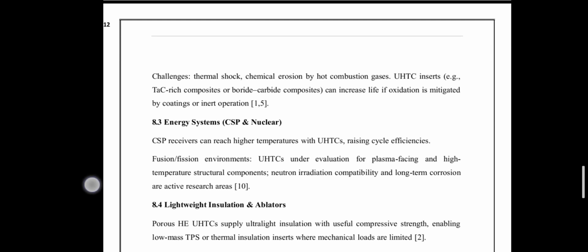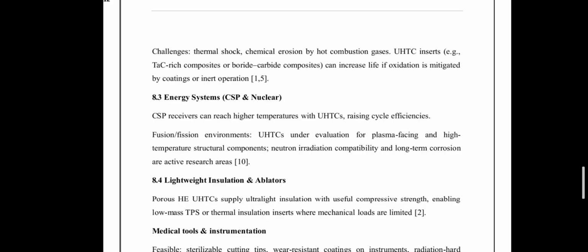So next we will study the energy systems, concentrated solar and nuclear, where the ultra high temperature ceramics are used. Ultra high temperature ceramics allow receivers to reach higher temperatures, improving the thermodynamic cycle efficiency. In fusion reactors, ultra high temperature ceramics are under evaluation for plasma facing and high temperature structural components. The key concerns are neutron irradiation tolerance, long term creep, and thermomechanical reliability. Lightweight insulation and ablators: porous high entropy ultra high temperature ceramics provide ultra light thermal insulation with usable compressive strength, ideal for low mass TPS panels or thermal insulation inserts where the structural loads are moderate.